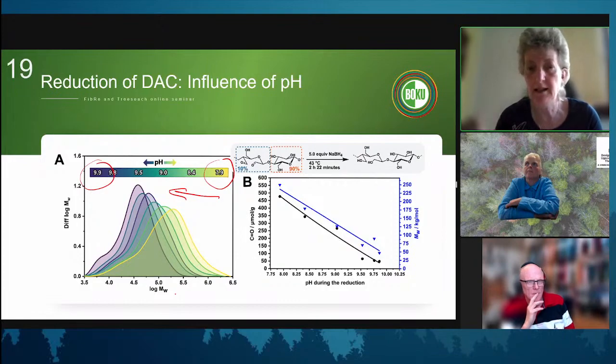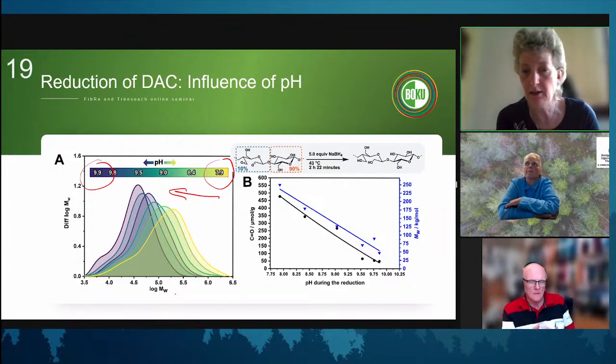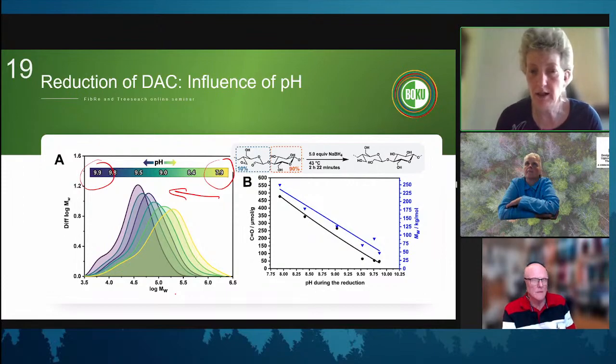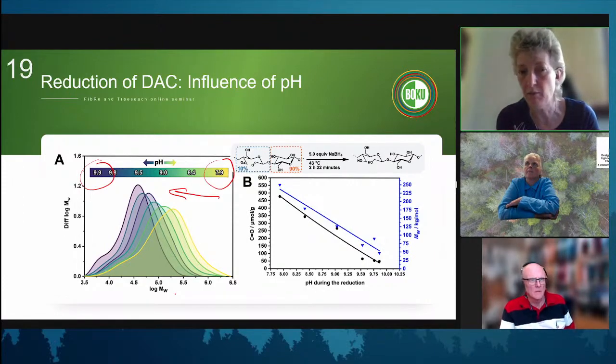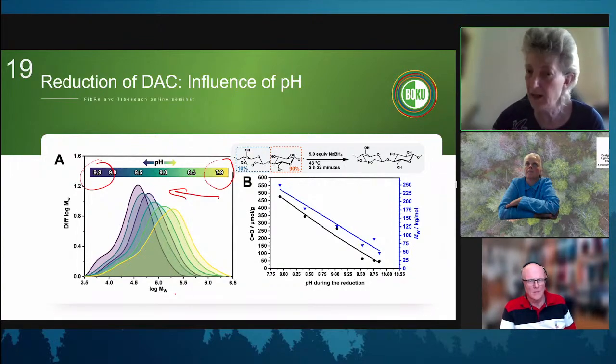So if you have an oxidized material and you take it into an alkaline solution and watch the molar mass degradation, you see a little bit where that happened. And when we look here at this periodate, we can say that such a large drop means oxidation also occurred really along the chain, not just at the ends, which are the amorphous ends, maybe better accessible. So it tells us where it happened.